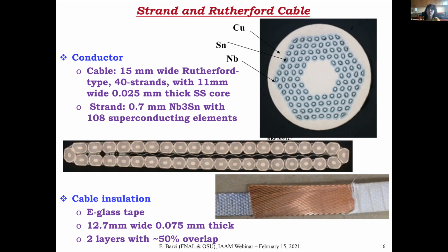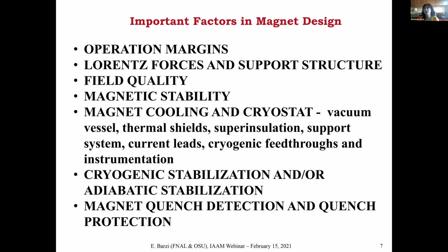From the composite wire, niobium tin composite, to cable fabrication that puts it in plastic strain. Then you insulate the cable, then you wind the magnet, then you heat treat the magnet, and during heat treatment you have this niobium tin diffusion to form the superconductor, and then the material that you form is brittle. It's absolutely brittle and strain sensitive, so if you touch it, it loses in its current capabilities because strain affects current capabilities. So this is the context in which we are working.